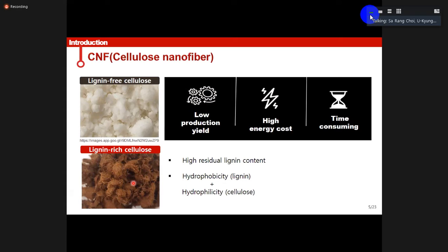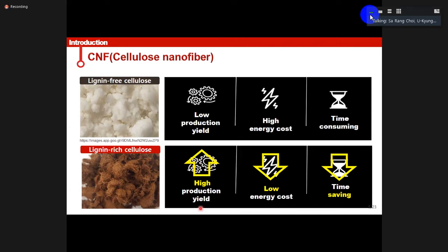Lignin-rich cellulose could be an alternative to bleached cellulose. Lignin-rich cellulose with high lignin content has both the advantage of hydrophobic lignin and hydrophilic cellulose. Therefore, lignin-rich cellulose provides an improved production yield of nanocellulose. And it gives more potential in various applications compared to the bleached pulp, although it might be weaker than bleached cellulose. So we tried to make fibrillation in a simple method using lignin-rich cellulose.